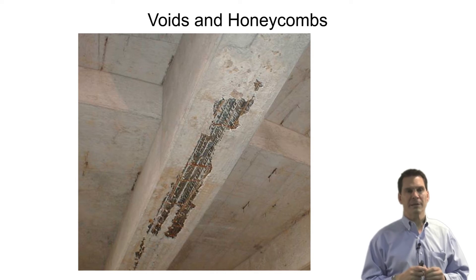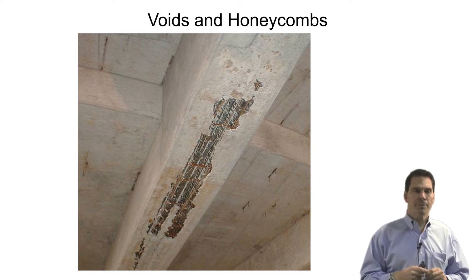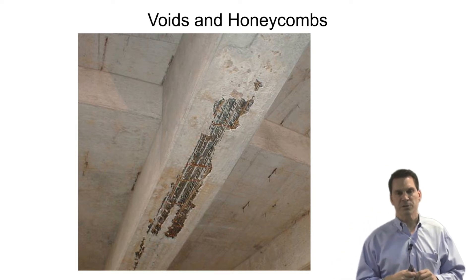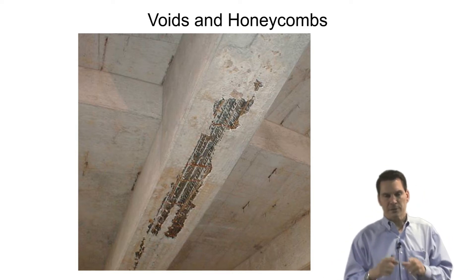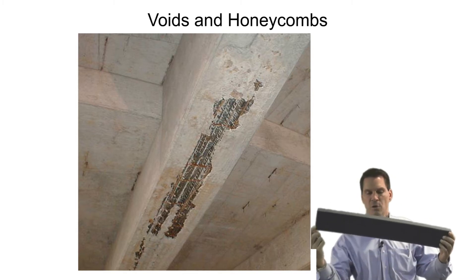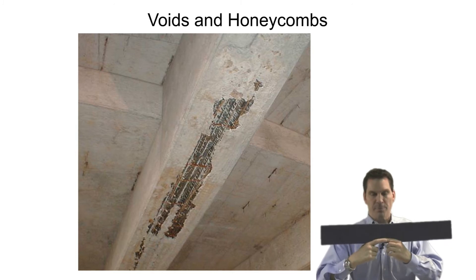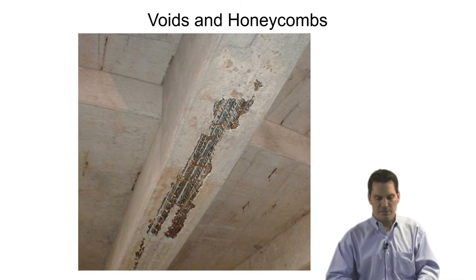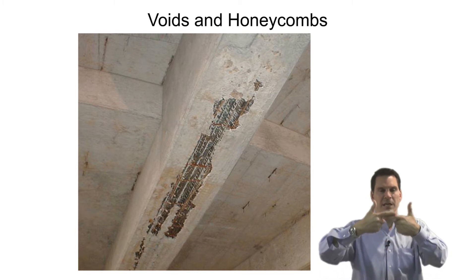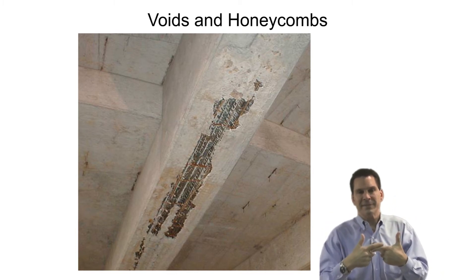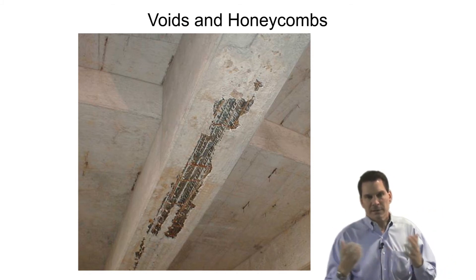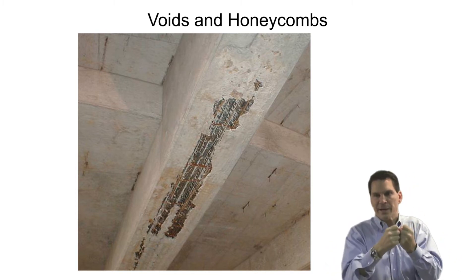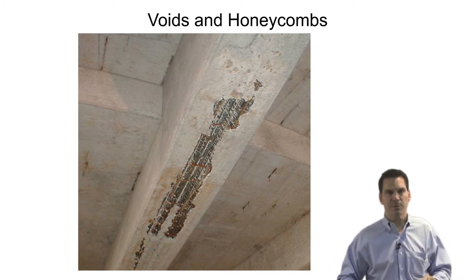Other voids can be created by the reinforcing steel details. The picture on the right is actually a workmanship error in which a large span beam with large reinforcing steel — where the contractor, instead of using continuous bars across the whole section, decided to splice the bars on the bottom, and instead of staggering the splices, the splices have all been put in the same place in the beam. As you can see, there's no way to even get concrete through that — it barely flowed around it. The other scary part is that in order to get a lap splice to work, you have to have concrete around it to hold it. So that's a pretty serious structural issue.